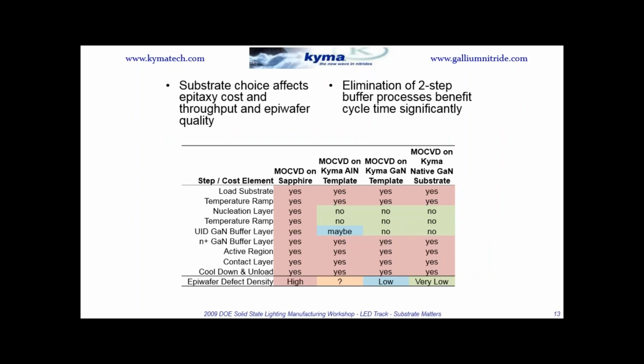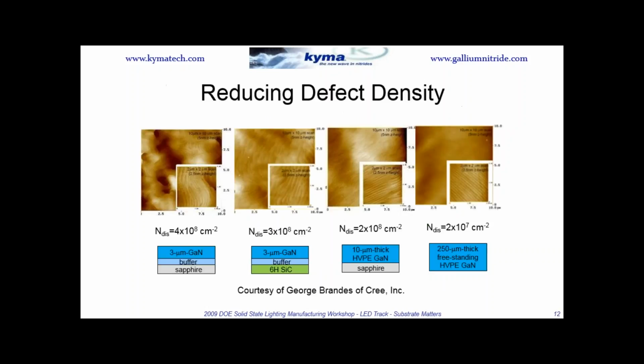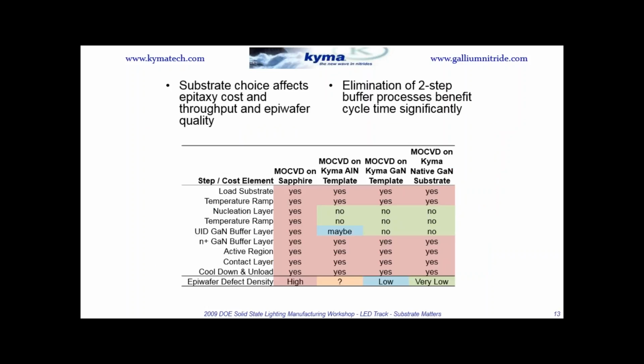This is a, I won't take you all through the slide, but I'm going to go back here. If you were growing your epi on here, your device epi, you wouldn't be so tempted to grow your own buffer layer because you got a really good starting place. But over here, you might need to grow a buffer for a while. So this next slide just shows that the time taken to grow these different layers goes down. Let's see, do I have a cycle time here? So the defect density is getting better and better as you go from left to right, and then you could add up these times and the cycle time goes down.